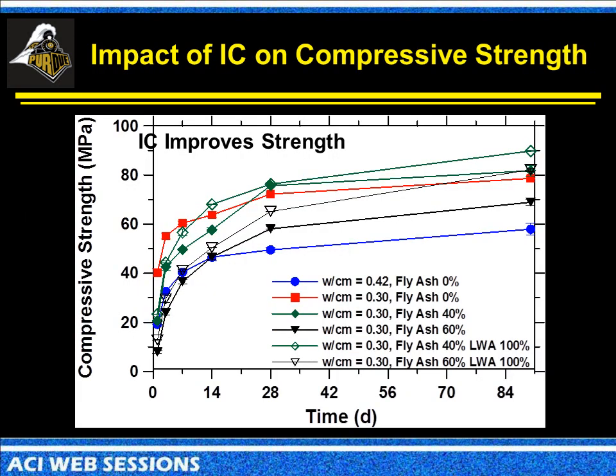Now, one of the things that we were a little bit surprised at when we started to look at some of the original data. The little secret to the convention here is that where we're adding the porous inclusions, we're going to call those the porous symbols. So here we've got the fly ash at 40% with our lightweight aggregate, and our two green curves match up and compare with each other. The two black curves match up. So this is our 60% fly ash, 60% fly ash with internal curing.